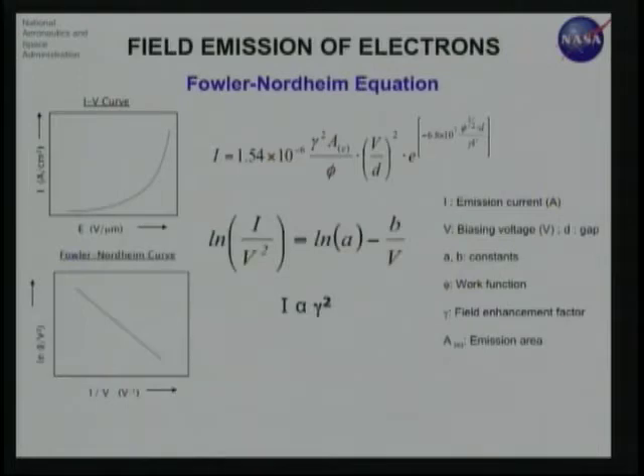If you take the natural logarithm of that equation, it converts into y equals mx plus c. Plotting that, the slope of this y equals mx plus c gives you a way to calculate gamma. So whenever you get a field emission curve, you go back and calculate gamma by assuming a certain work function for the emitter itself. So gamma is the key.